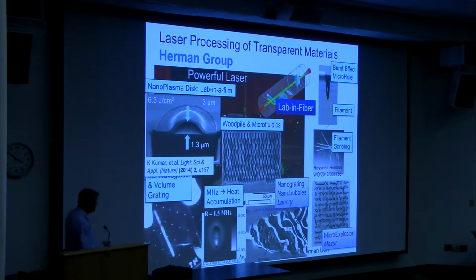At the end of the talk, depending on how much time I have, I'd like to also introduce another modality where, for example, in this case, we have filaments following the laser. Here we're making these little thin plasma discs, and we're opening up nanostructures in thin films of glass. For example, in CMOS technology, we have oxides present, and we're trying to invent a way to make nanofluidics and do lab in a film, which is another mode of interaction that I'll tell you about. That's a lot of fun.